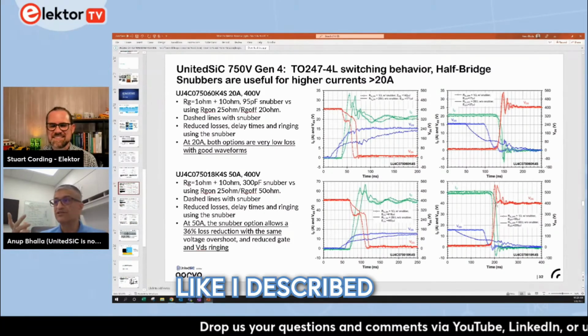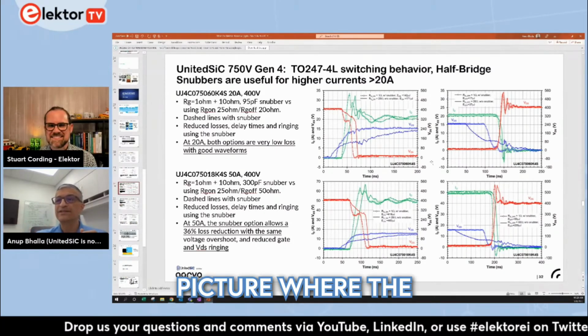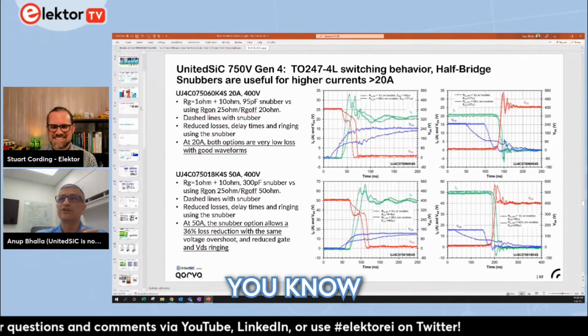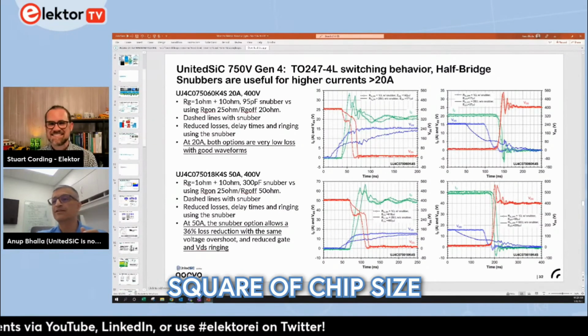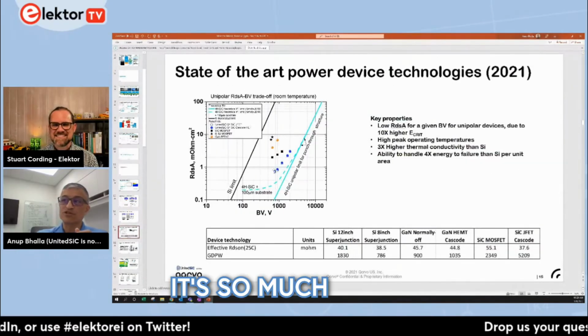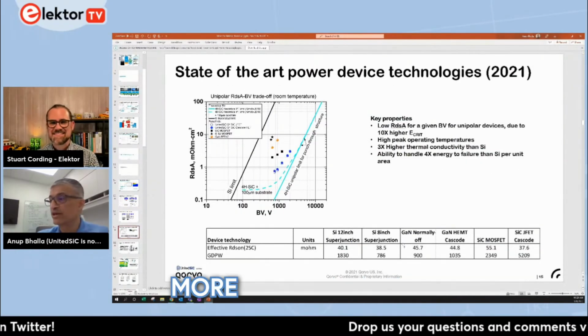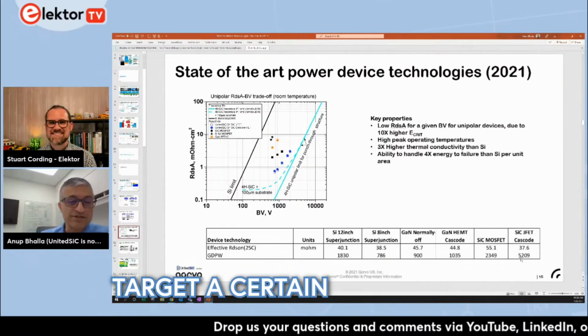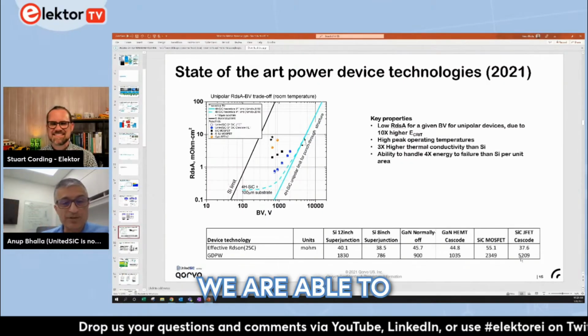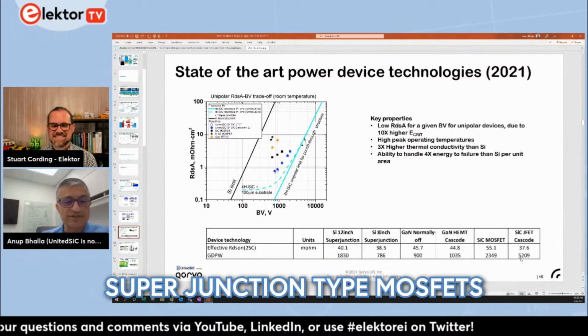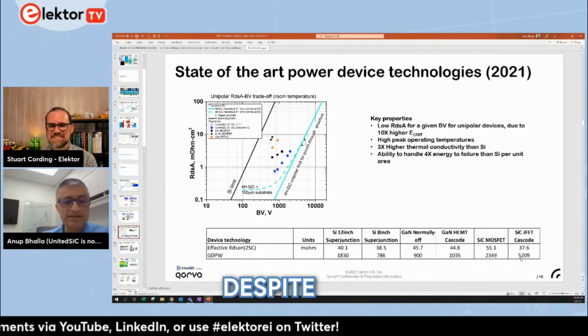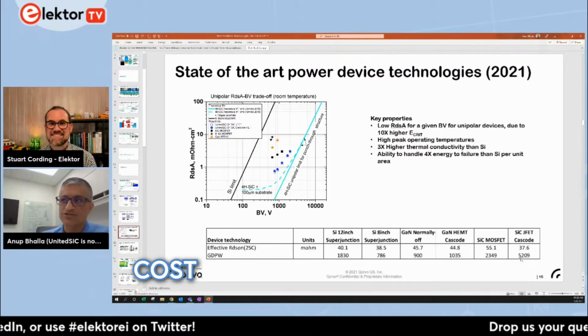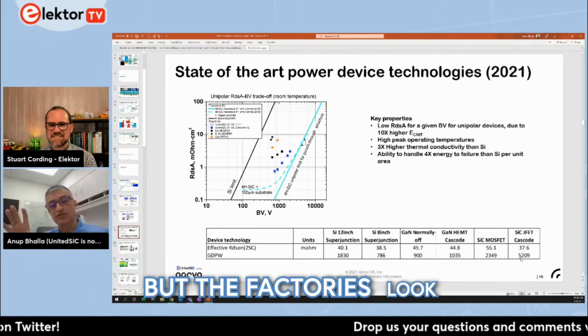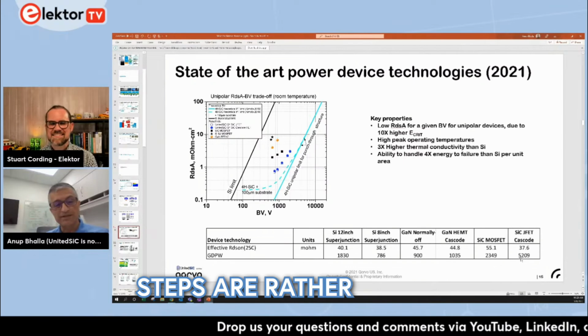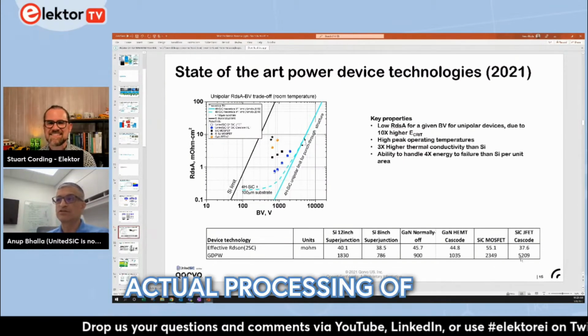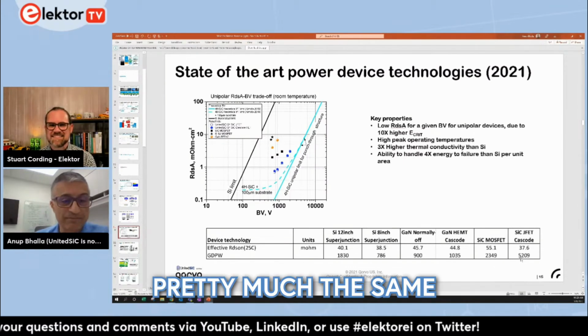At the end of it, though, like I showed you in that chart, the resistance that we get out of a centimeter square of chip size is so much lower than silicon devices that we get so many more die per wafer if you're trying to target a certain resistance. I think at this point we are able to be fairly competitive with superjunction type MOSFETs, despite the higher cost of building silicon carbide. But the fundamental steps are rather similar. Factories that do the actual processing of the wafers look pretty much the same.